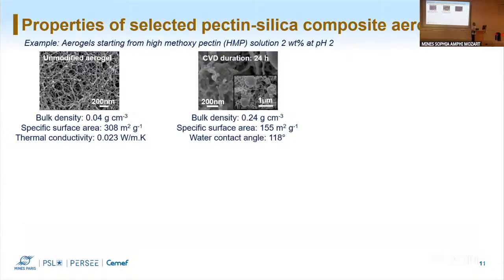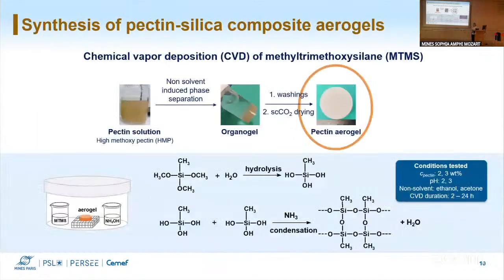Okay, you play with the time. It is a very judicious choice, but on which experimental parameters linked to your device is it possible to play in order to control the grafting well, in order to avoid aggregation? So in that case, as I said, we just put everything together, not in contact, and then we have the vapors. The other thing is that here water is inside the reaction and we don't control it. So it's the moisture of the air, and this is very important.